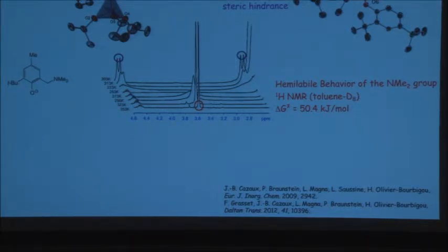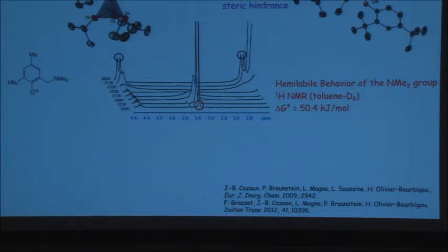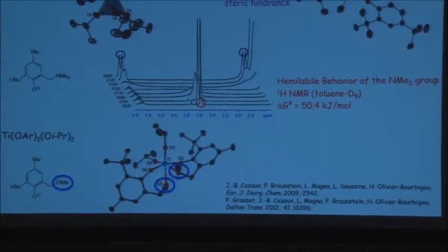We suspected that this dynamic behavior would involve coordination of the nitrogen to the titanium center. If the nitrogen remains non-coordinated, free, no way you can generate an AB system. So the 2 CH2 protons remain equivalent. You get a singlet. But if they coordinate to the metal center, then they should give rise to an AB system. But this crystal structure did not reveal any interaction.